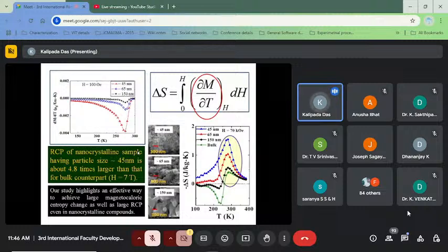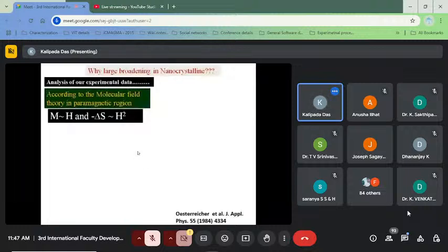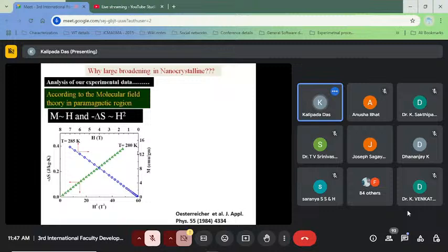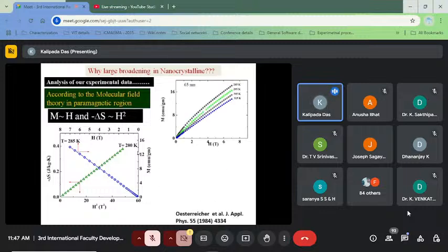And this phenomenon is not only present in this sample. We have checked other sets of antiferromagnetic samples, and we see that the same phenomenon occurs. Now the question is why such behavior appears in the nanocrystalline sample, why the magnetocaloric entropy change is enhanced. To do this, we have studied the paramagnetic state. We see that delta S is proportional to H squared, similar to the M versus H graph. However, this is for the bulk, antiferromagnetic sample.